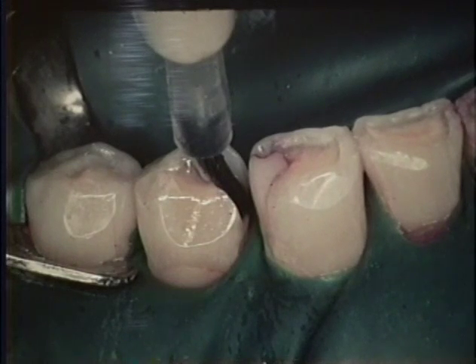Okay, now we're putting on our Photobond. The Instant Grip is definitely required, so there's Photobond being polymerized. Now the bond strength on the dentin there with Photobond is about half the enamel bond value. And half the enamel bond value is more than adequate for an auto-cured resin system. If you're using a light-cured resin system, that's pretty marginal.